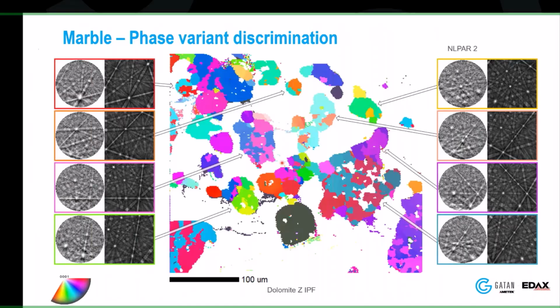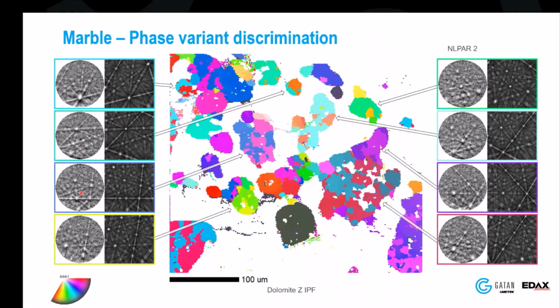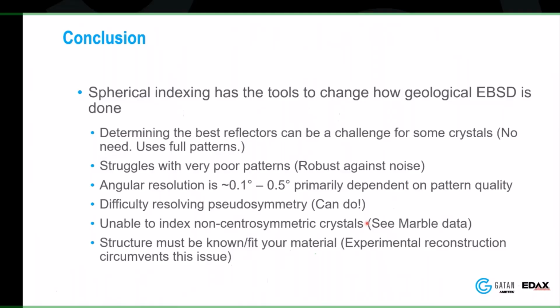Here's doing this for this whole data set. Again, you can see the same idea here. Let's take this grain right here and follow it back over here. You can see that all these zone axes are basically in the same place, but the difference between these two orientations is really found by a couple of these tertiary lines here. And this is the power of this fine level of detail that we have now in these patterns. Comparing them to the master patterns really allows us to find these small details that we would just be ignoring in previous EBSD maps.